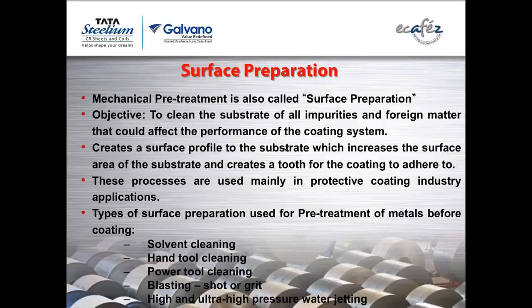Now, surface preparation. Mechanical pretreatment is called surface preparation. The objective is to clean the substrate of all impurities and foreign matter that could affect the performance of coating systems. It creates a surface profile on the substrate, the metal, which increases the surface area of the substrate and creates a tooth for the coating to adhere to. These processes are used mainly in protective coating industry applications. Types of surface preparation used for pre-treatment of metals before coating. First is solvent cleaning, which is mandatory for all the processes listed below.